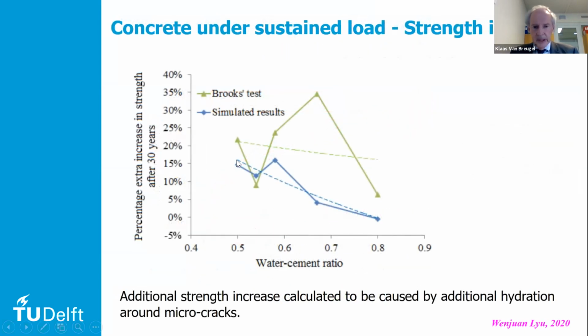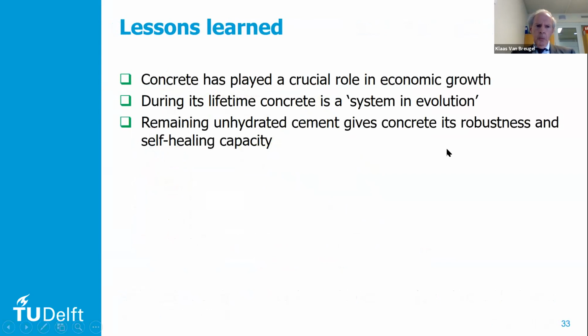What she also found is that this additional increase in strength, beyond the strength that you would expect from the normal hydration, was calculated with the blue line as a trend line, and what Brooks found was actually the green line. Well, there's a big scatter in the tests of Brooks. You can forgive it because the tests were actually not performed with the purpose we were using them for. But I think the trend is certainly the same. So that was nice. What do we learn from this?